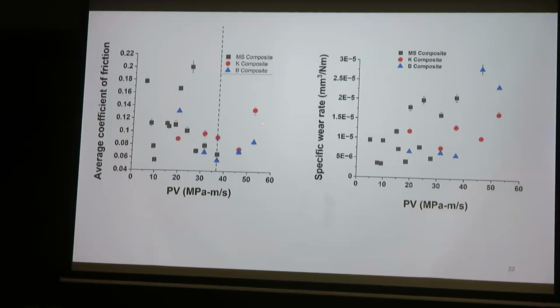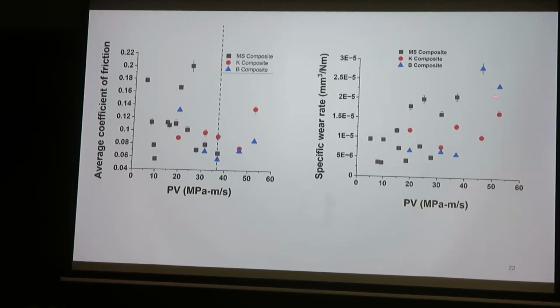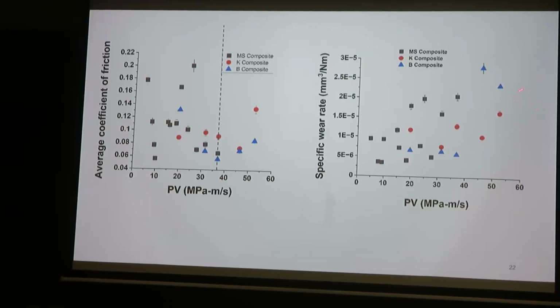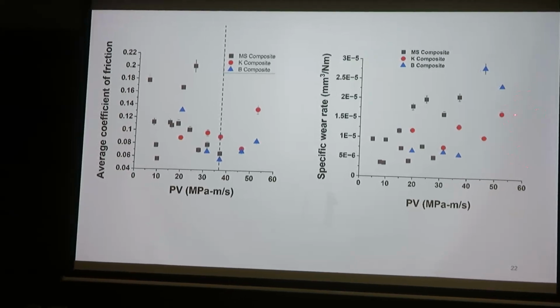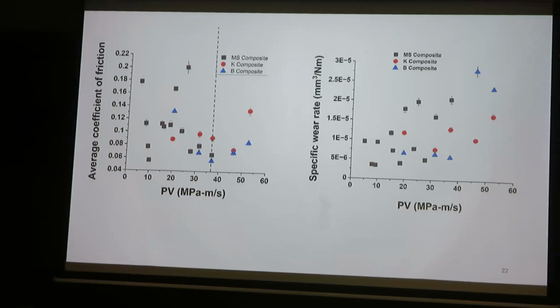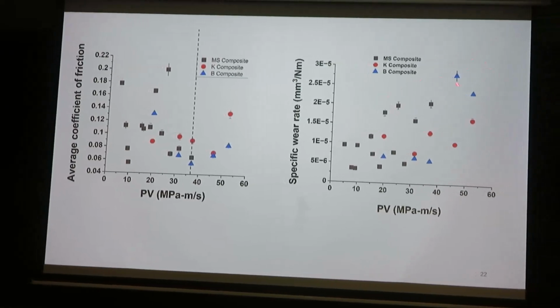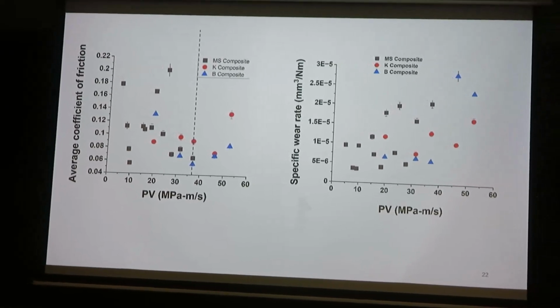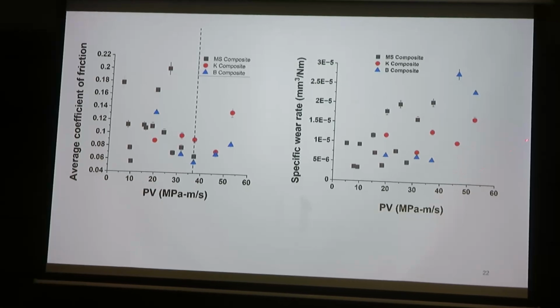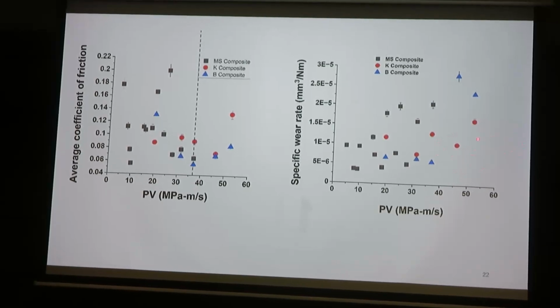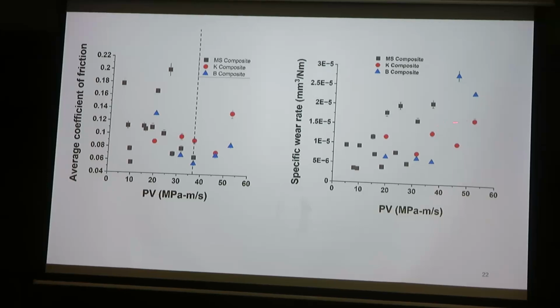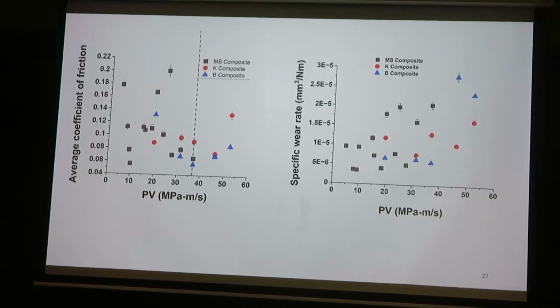Okay? So coefficient of friction and also wear. Although you will see that the wear starts going up, okay? So obviously at some point the wear rate will accelerate and it will fail very drastically. But still these composites with epoxy and these fillers have given us very high PV factor.